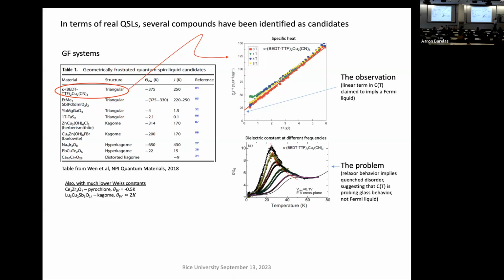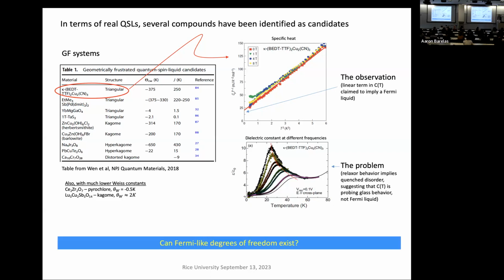Not surprising, actually, because the ET molecule is the magnetic molecule, not the copper group. And the ET is a free object with free radicals that sit presumably on both ends and lead to quenched structural disorder. So this is the sort of mayhem that is just right in this field, with claims based on lack of data. So what is it? It's probably a glass signature, because glasses also have linear terms in the specific heat.